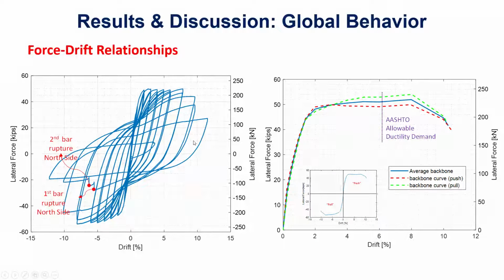But more importantly, this is the behavior as we capture the force-displacement relationship. And you see this hysteretic behavior is a good sign for good energy dissipation as required by the current ductile-based design. When we did the envelope from the two sides and we averaged them, we get the average pushover curve, and you can see here we meet the allowable ductility demand for this type of connection. So we are definitely satisfying the design requirements that we need.